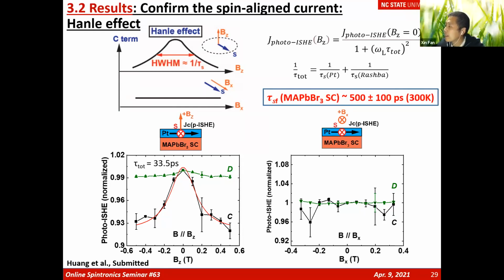Kirill, you have a question? Yes, I wanted to ask whether it's possible to push holes into these Rashba bands or control them by electric field or gating. That's the ultimate goal for demonstrating the Rashba effect in such semiconductor materials. Usually in an oxide 2D electron gas, they are able to control the Rashba state by applying a gate voltage. Here, definitely yes, we can apply gate voltage to tune the Fermi level at the interface, but I haven't tried that. It is a possibility: once we form the Rashba state, the Fermi level can be tuned by gate voltage. This is a typical semiconductor material, so there's no reason why it wouldn't work, but it needs time to prove it.